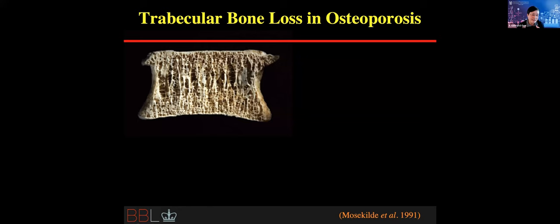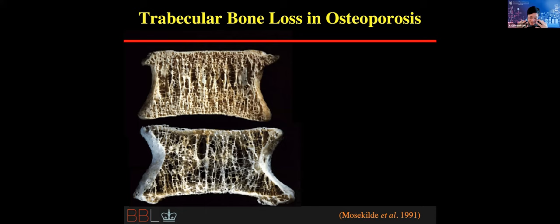The second one even looks disorganized, but they do show the axial direction and then all the bones along this way. So in osteoporosis, or when getting old, they lose bone. That's most important, right? It's very apparent, you lost some amount of bone. You look at this aging bone, it's actually not bad, but you can see how much bone they lost. But if you're observing carefully, those plate-like structures all disappeared, replaced by mostly this rod-like structure.